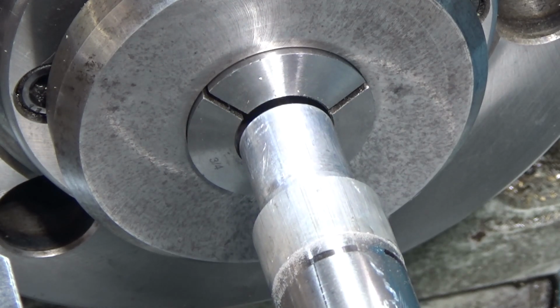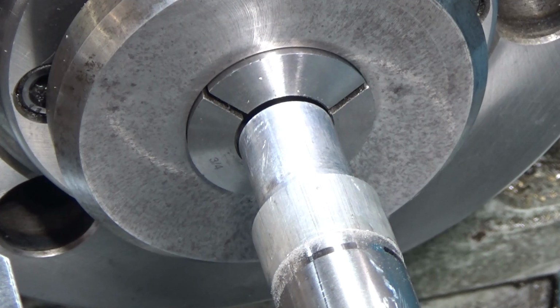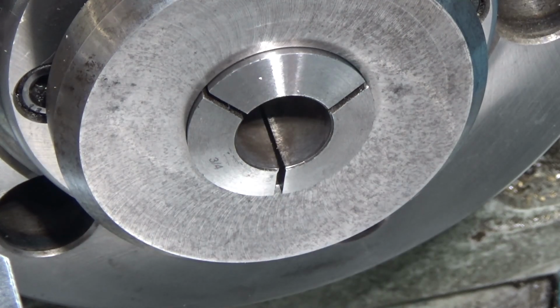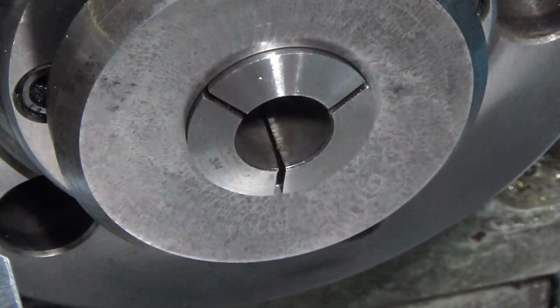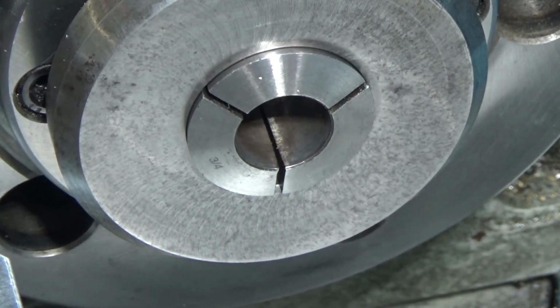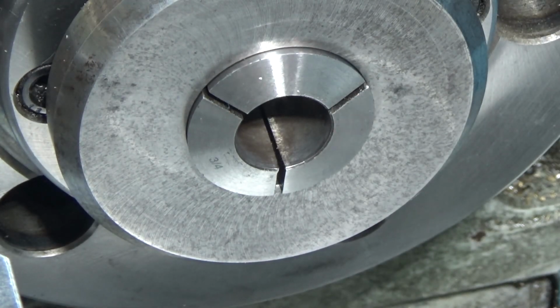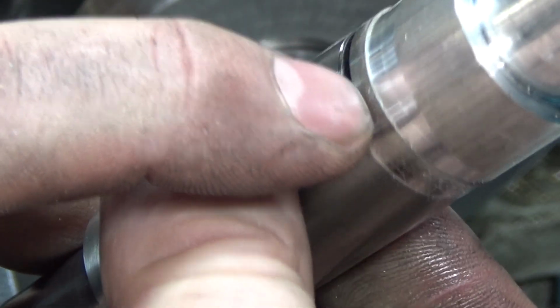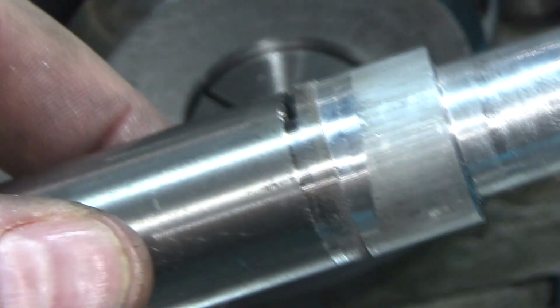That's a good sign. It welds every time, it's just not a very strong weld. And it could be simply oxide layer on the surface of titanium, oxide layer on the aluminum, preventing the weld from being very good. I actually see some pressed out aluminum this time. So maybe it's a better weld. I cleaned off the face.